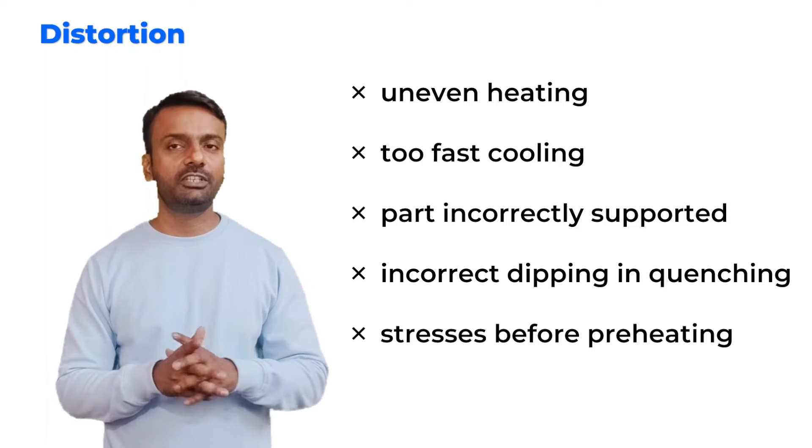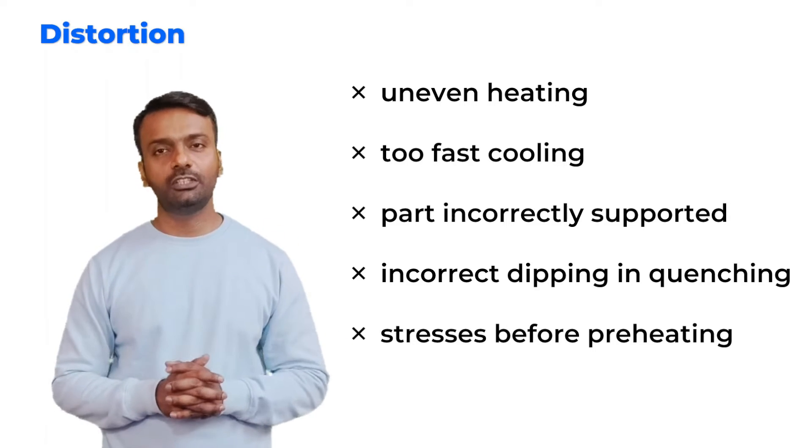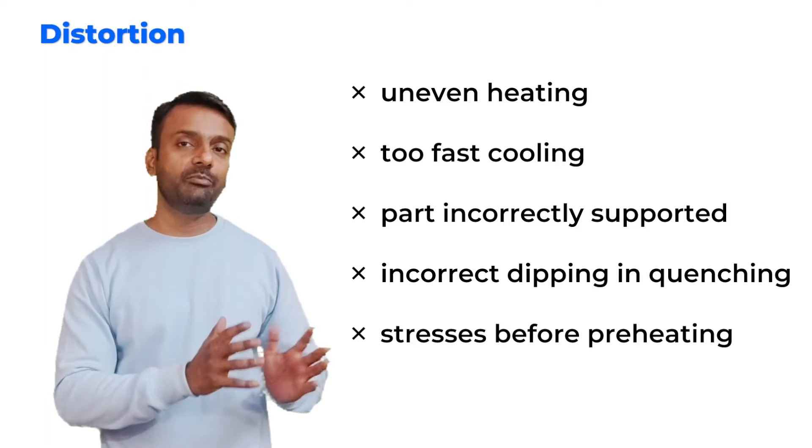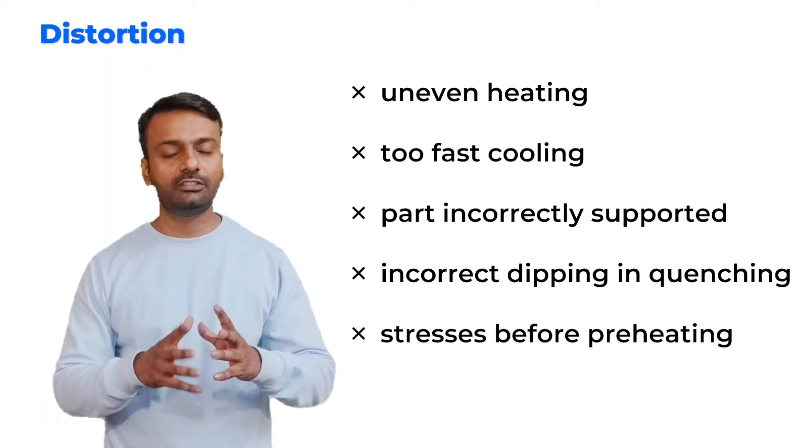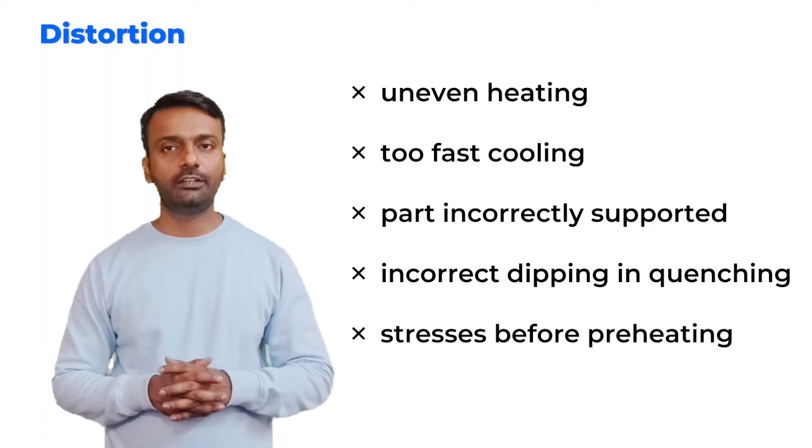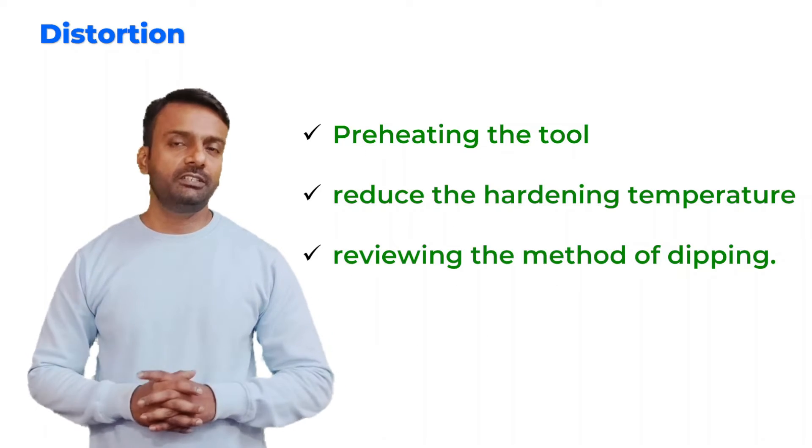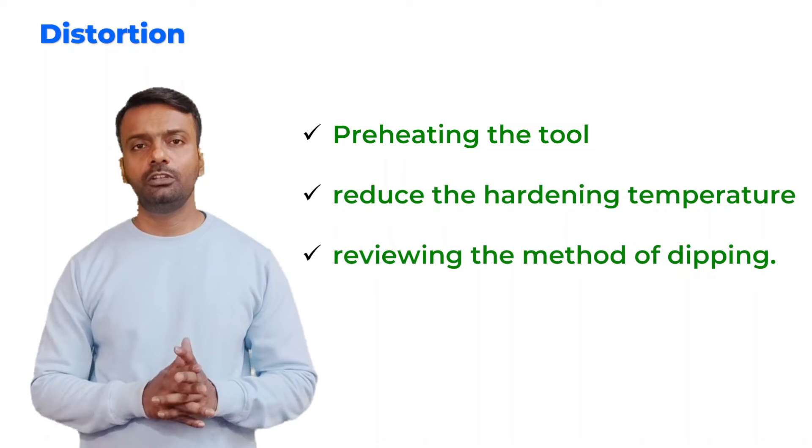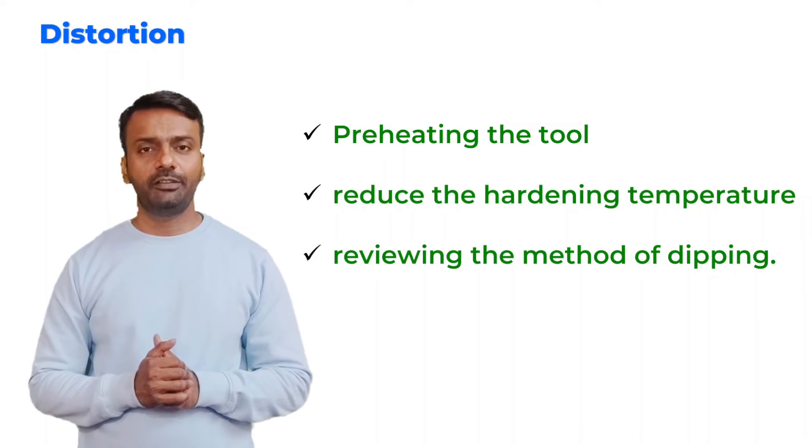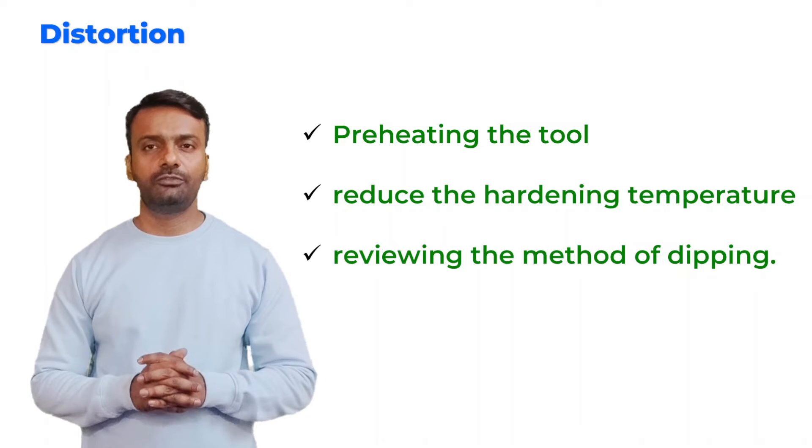The final issue is stresses during preheating. Before you are doing the heat treatment, the sample is already having some stresses inside. You have to relieve internal stresses before you do heat treatment. There are some methods by which we can prevent the distortion defect: we can preheat the tool, reduce the hardening temperature, and review the methods of dipping.